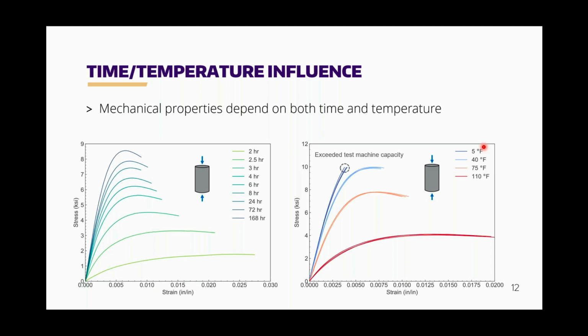They were both done at laboratory temperature. And one of the things that's important to understand about polymer concretes is that the mechanical properties depend on both time and temperature. So we're used to time with our cementitious concrete. The only difference is, as you can see with the legend here, we're talking about a matter of hours versus a matter of days and weeks. And what I'm showing in both curves is the stress-strain behavior of a concrete cylinder in a test machine.